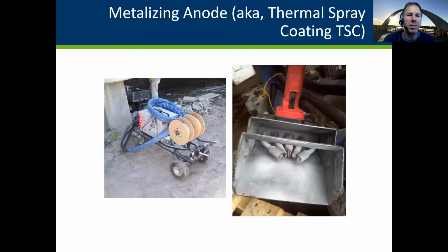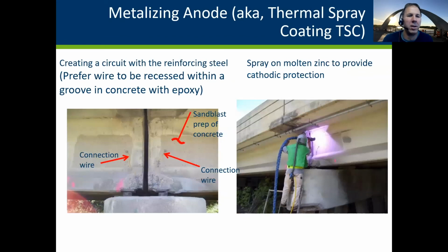So that's a welding type operation. The zinc wire comes on these spools for this type rig, and it comes out 2 nozzles. And then there's 3 compressed air nozzles underneath this handheld hood thing that sprays it. And then when those 2 wire spools kind of contact with this high current, it vaporizes and the compressed air blows it onto the concrete, and it's adhered.